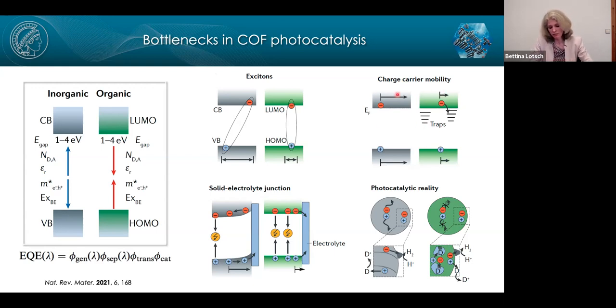Also, charge carrier mobilities are very different in inorganic and organic systems. In inorganic systems, often we have much higher charge carrier mobilities than in organic systems for intrinsic electronic reasons, but also because organic systems, especially polymers and amorphous systems, are loaded with traps that, of course, slow down the charge carriers. Also, we cannot take advantage of band bending that we see at the solid-liquid interface in many inorganic systems, simply because we have very low amounts of free charge carriers in organic systems. And therefore, there's no additional driving force to separate the charges at this interface.